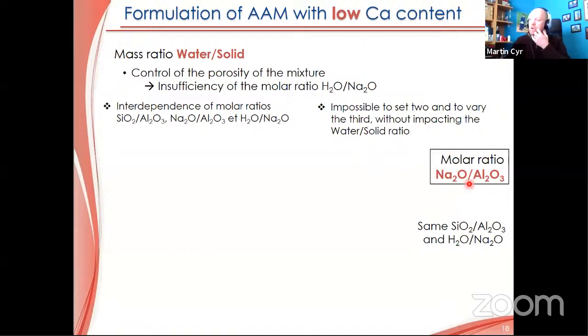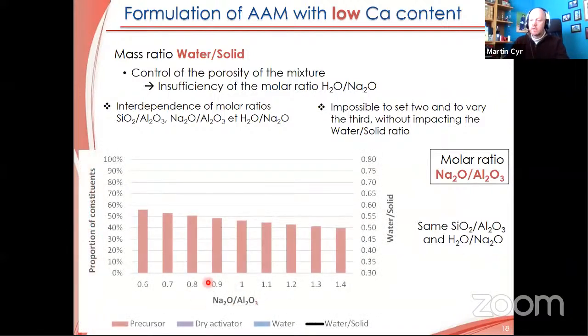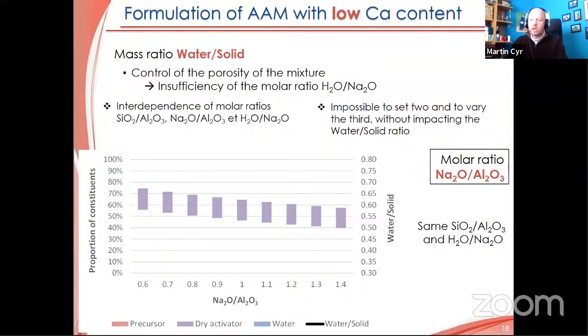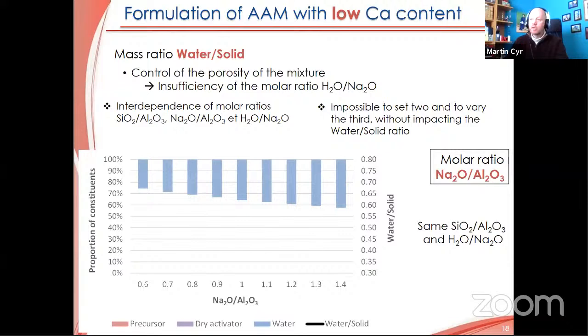For instance, if I have a closer look at the sodium aluminium ratio, by keeping, in the next graph I will show, silicon over aluminum constant and also water to sodium constant. So if I change only the sodium aluminium ratio by keeping the other two constant, it means that we will probably decrease the amount of precursor in order to keep these two constant and change only this one. In terms of dry activator, it would not change a lot, as we can see. And in terms of water, if we want to have 100% of the constituent, it means that we will have to increase the water content.